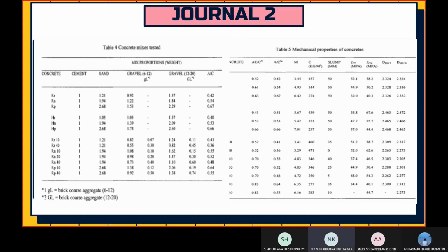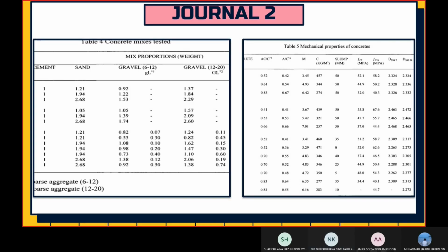The compressive strength is calculated using a 10 cm cube specimen according to BS 1881-116. According to UNE 83-301, the modulus of elasticity is measured in a cylindrical specimen of 15 cm times 30 cm. The density and porosity of the prismatic specimen were determined at 7.6 times 7.6 times 25.4 cm.